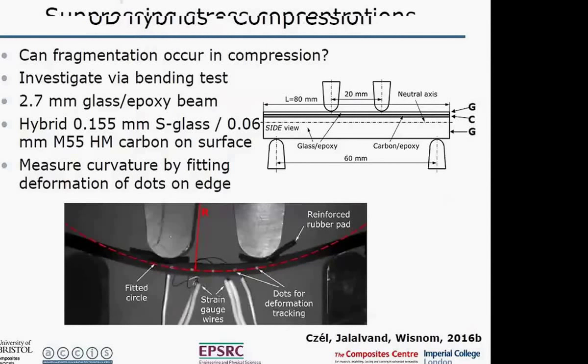So we initially investigated that using these beam specimens. A 4-point bending test with a 2.7 millimeter glass epoxy beam with a layer of hybrid on the surface. So here we've got a glass carbon hybrid just on the compression surface, the same material we looked at before with a standard glass applied on the surface, and then 0.06 millimeter of M55 high modulus carbon underneath it. And then we put it under 4-point bending and measured the curvature by dots on the edge of the specimen, and then used that to determine the strain, and therefore look at the overall response.